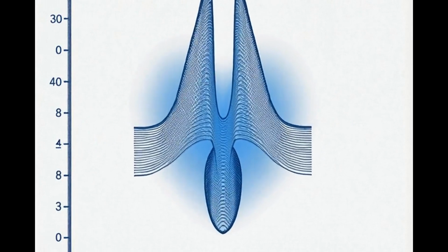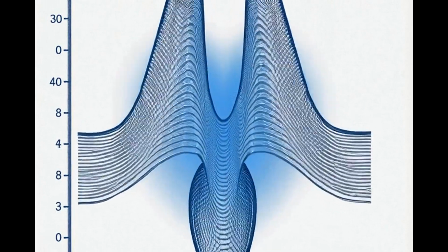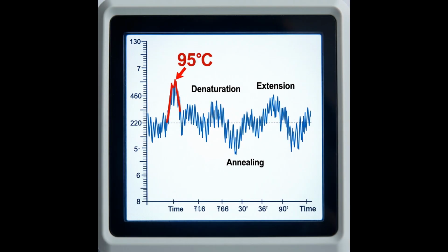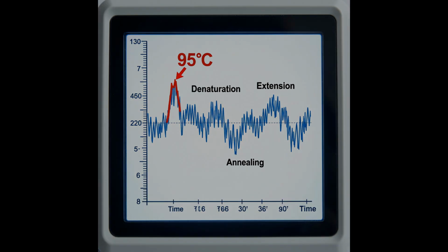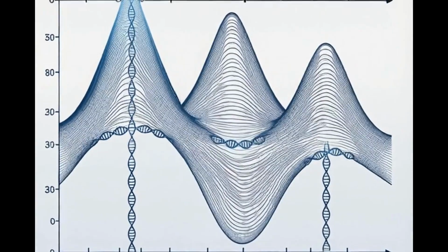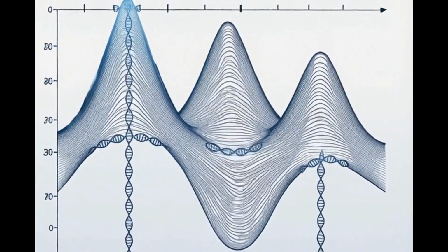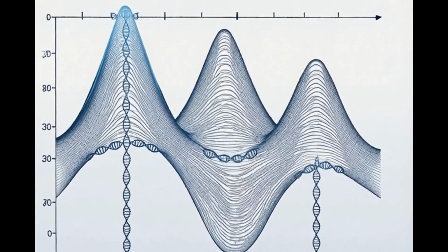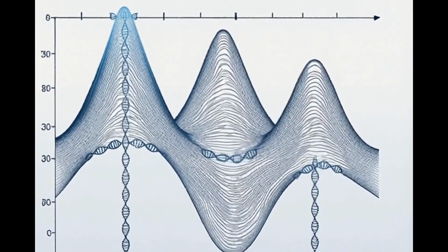Next, the temperature drops rapidly to around 55 degrees Celsius, allowing short synthetic primers to locate their specific target sequences through a process called annealing, where base pairing occurs. Finally, the system stabilizes at 72 degrees Celsius, which represents the optimal activity range for heat-stable DNA polymerase enzymes to synthesize new complementary strands from available nucleotides.